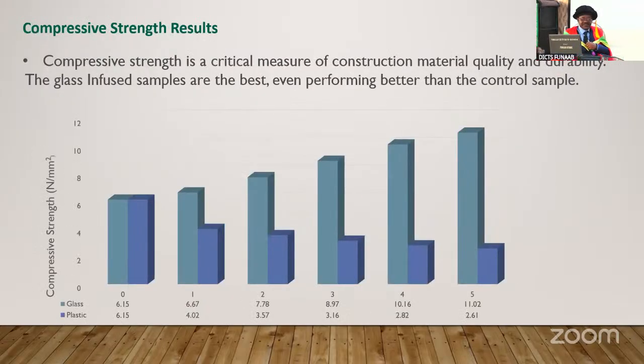For the compressive strength, which is the main thing. Compressive strength is the critical measure of construction material quality and durability. The glass infused samples are the best, even performing better than the control. When we look at the figure above, the control has 6.15 MPa, while glass infused gave us 11.02 MPa at 5%, but the one with plastic gave us 2.61.